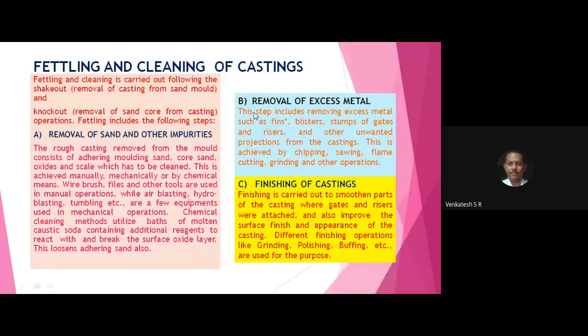Next, write down B, removal of excess metal. That is, the casting has gates, ingates, runner, riser, sprue, and other unwanted projections present on the casting, which are removed by chiseling, using a chisel and hammer. By chiseling, they remove the excess metal. That's one method. The other method is by using a cutting machine or grinding machine. Usually with a cutting machine, they cut the risers, sprue, gates, and ingates from the casting. So that is the removal of excess metal.